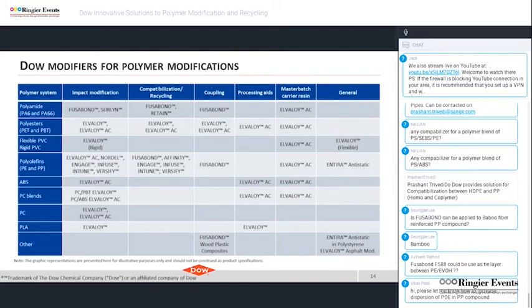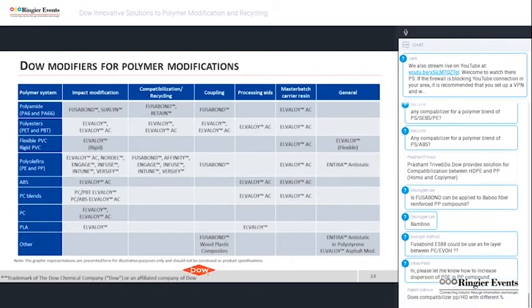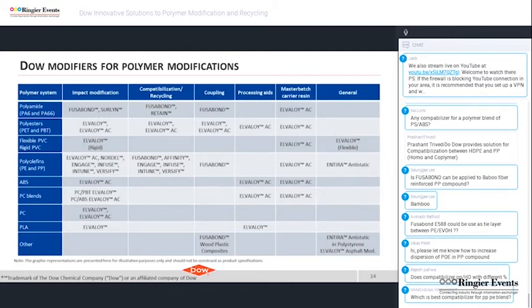For PE-PP mixture recycle stream, you can use ENGAGE polyolefin elastomers, VERSIFY elastomers, and INFUSE propylene olefin block copolymer as modifier to improve the toughness, tensile, elongation, and low temperature performance of PE-PP blend. One major challenge in plastics recycling is polymer cross-contamination, as different types of plastics are often combined in manufacturing process. Today, I have shown you that Fusabond compatibilizer can be used to improve the mechanical performance, such as tear and tensile of recycled stream from packaging film containing PE, PA, and EVOH.